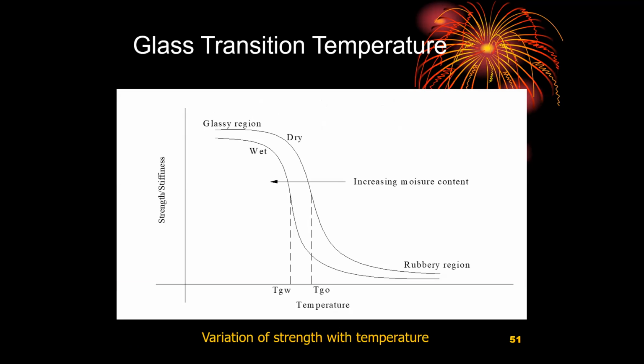As the increasing moisture content, as pointed out by the arrow, plays a bigger role in converting the dry TG into wet TG for any plastic material, the wet TG is found to be lower than the dry TG. So normally if you have a dry TG of about 120 degrees Celsius, you might often find that the wet TG is about 100, 115 degrees Celsius only.